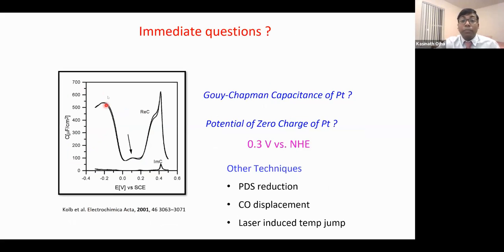So that was a challenge, and people tried for more than 50 years, and nobody found the diffuse layer capacitance of platinum, or basically the potential of zero charge for platinum. They tried the measurements, but instead of a minimum in the capacitance curve, they found a peak. And that is a bit surprising, because if you go to low concentration, you should see a minimum in the capacitance curve right at the potential of zero charge. Although there are other techniques to detect the potential of zero charge, they found it at 0.3 volt by other techniques. Those techniques are also standard, but they never found it using the classical Gouy-Chapman theory.